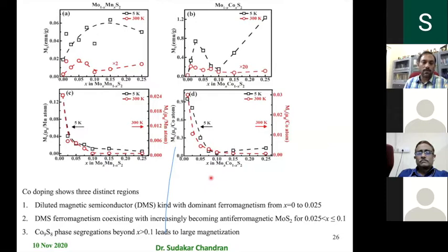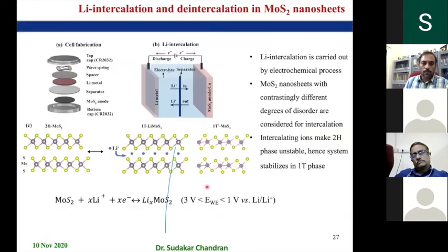That is always there. But this particular behavior, initially the magnetization increases and then decreases, basically tells that initially you have a dilute magnetic semiconducting nature dominating, and it decreases because the antiferromagnetism takes over. Therefore, in this region, you have both antiferromagnetic and DMS state. But beyond 10%, the cobalt sulfide phases segregate, and therefore you see this increase in the magnetization. So doping is always tricky, so one has to work at the right doping concentration.